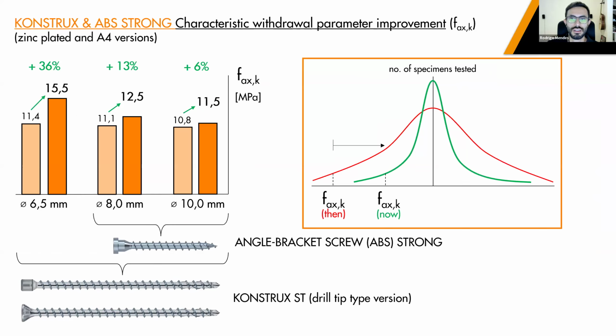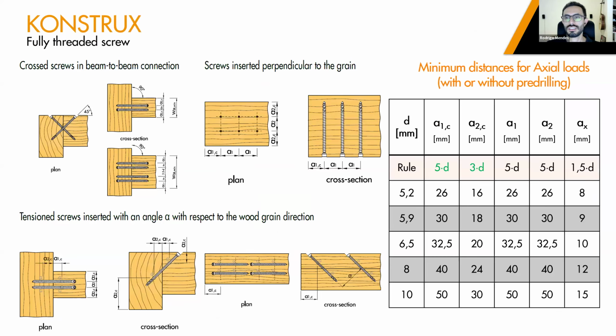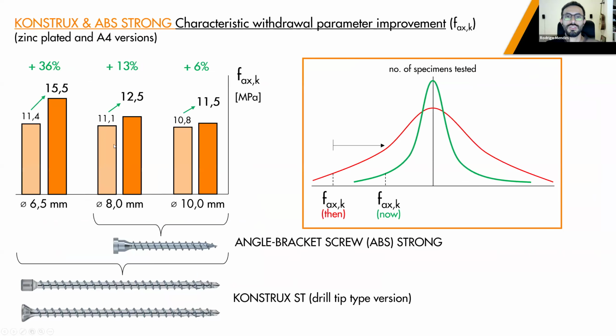Well, in that case, with the higher moisture content, for fully threaded screws that are mostly used, as I mentioned, in axially loaded applications, there's a factor, I think it's the K mod factor, that depends on the service class of the joint you're designing. So according to European standards, the Eurocode, this factor goes, I think, from 0.6 to 1. So the more moisture content you have in the screw, in the timber, the less resistance you'll get. For example, this is made with this factor.